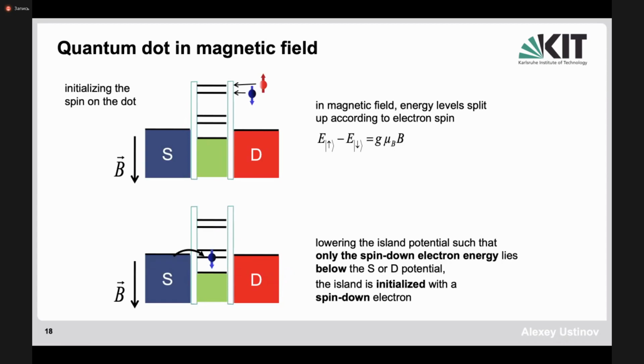We need to be able to control spin states. And spin states can be generated by removing the degeneracy by applying a magnetic field. So you apply a magnetic field, and then spin up and spin down states have different energy. You have Zeeman splitting. And basically, if you control now the gate, you move the Fermi energy in the dot up and down. Then you could make it possible to tunnel from the spin down state and not have any occupation of the spin up state, for example. So depending on the separation between the two states, you can manipulate now with source and drain and gate, and basically distinguish different spin states.